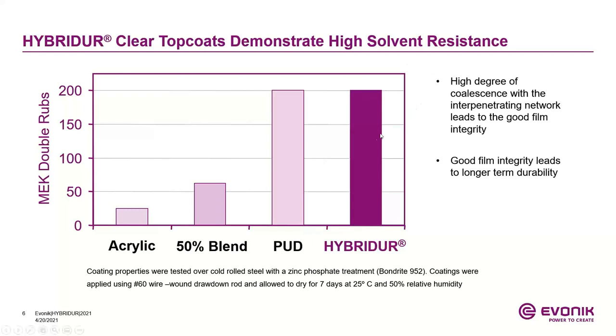And what we see here is the Hybridur polymer dispersions provide a similar solvent resistance as polyurethane dispersions. And the MEK double rubs are significantly better than a conventional acrylic as well as a blend of an acrylic and a polyurethane dispersion. The reason for this is it does provide a high degree of coalescence with the interpenetrating network. It leads to good film integrity, and good film integrity leads to a longer durability as indicated by the solvent resistance test.